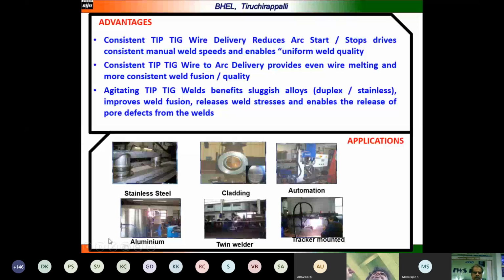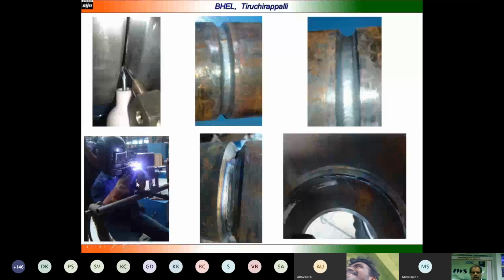It can be used for welding of stainless steel, aluminium, it can be used for cladding applications, automation, tractor mounted, twin welding, everything can be done using this application. And what you are seeing here is the tungsten electrode, the filler wire is coming for welding a pipe joint, and the welder is making the weld, and the weld can be completed, and you can see the penetration also here in the inside weld, inside the pipe.